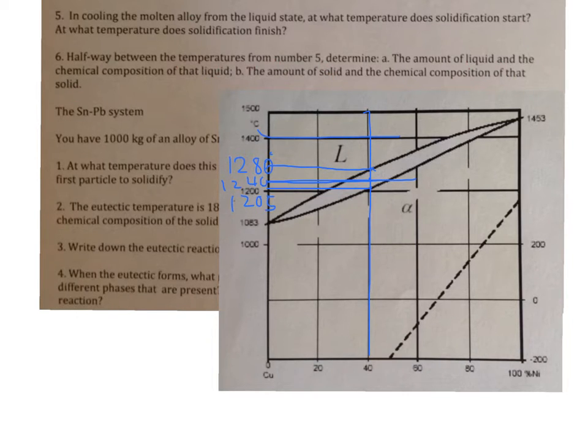Well, of course, this question recognizes that this region that is in between the liquid and the solid is a combination of the two. And that's how it will always be on these phase diagrams that these single phase regions will be separated by a two phase region that mixes the two. You can consider this the boundary between the liquid and the alpha that contains liquid and alpha. So what we have in this region is liquid plus alpha.